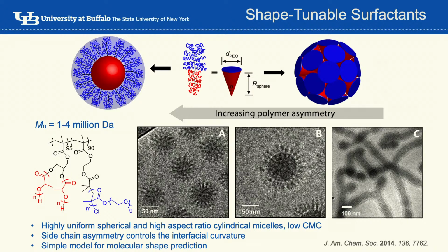So this is why micelle stability is important. A lot of polymeric micelles are used for drug delivery applications, right? So you encapsulate hydrophobic drug in the micelle. But the problem with all these micelles is that once you inject them into your bloodstream, it gets diluted. And once it gets diluted, it falls apart, right? Because you go below CMC. So low CMC is important, right? Stability is important. But I'll show you in a minute how you can make them even more stable.